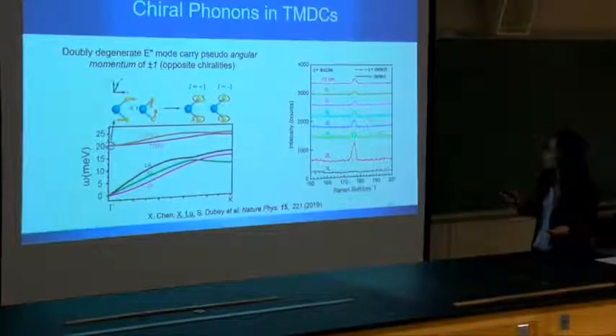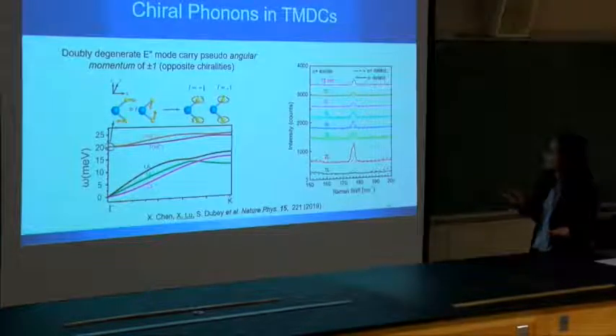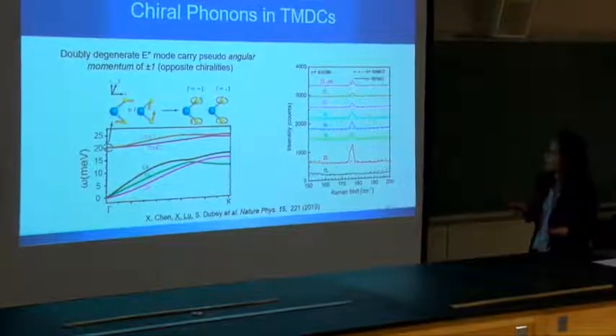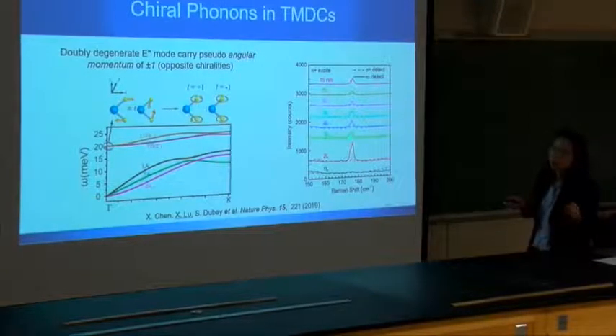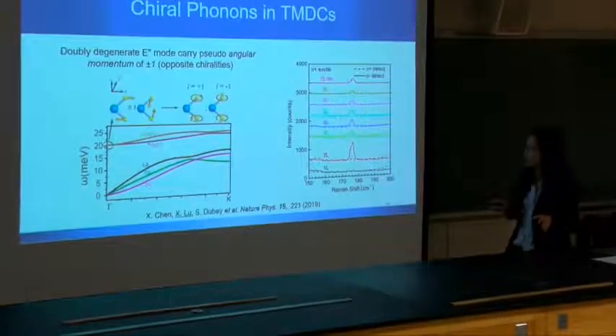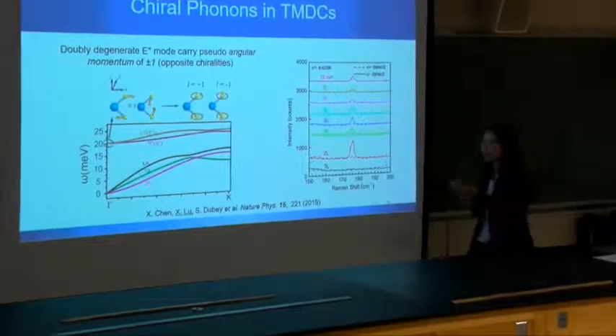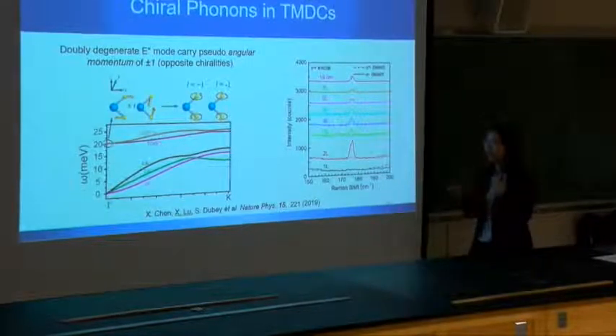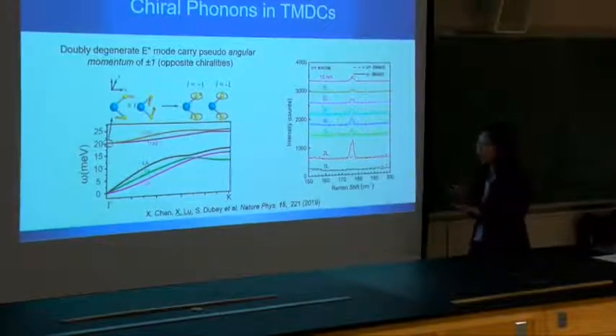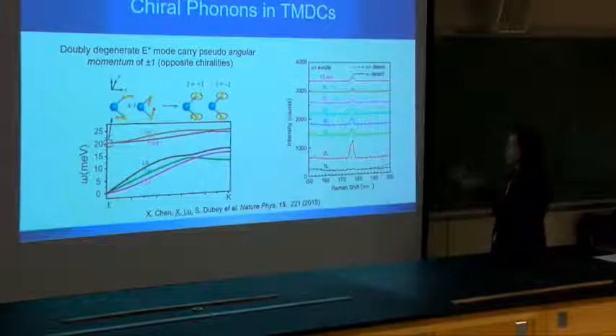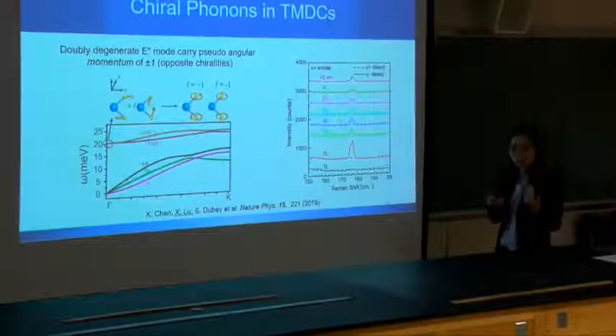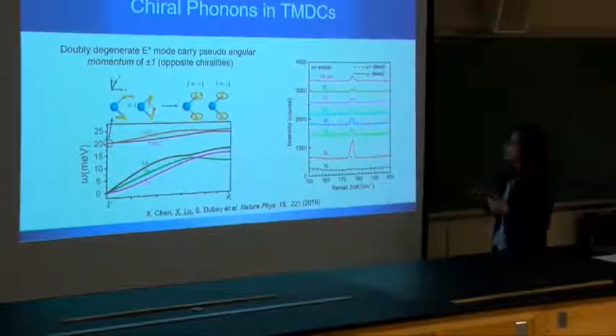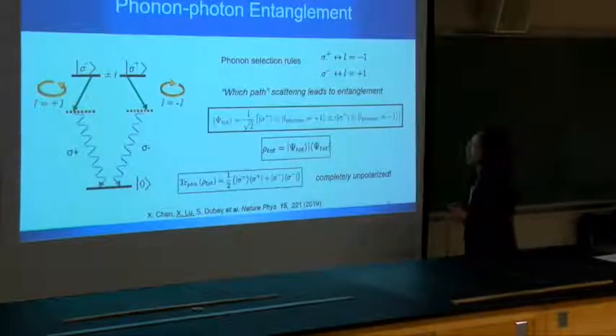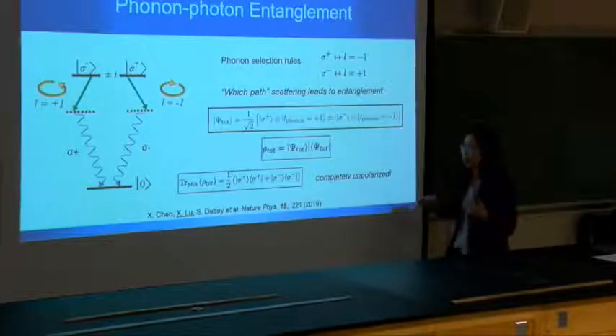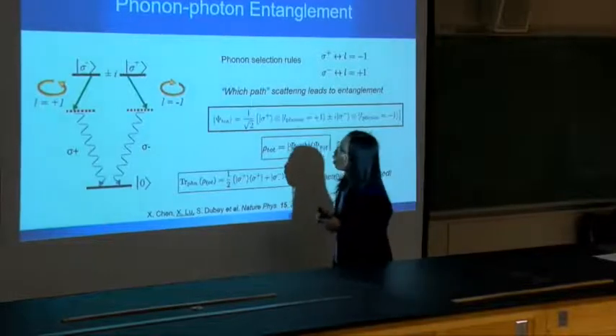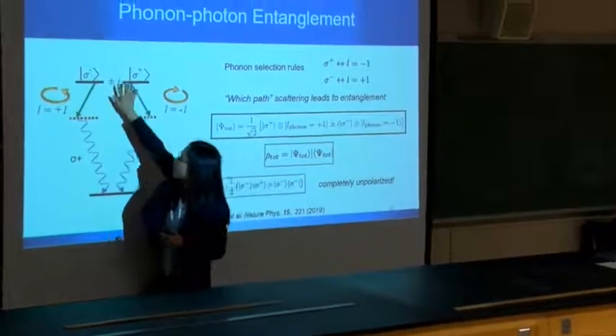But in fact, we see the phonon from the opposite helicity. From the co-polarized, we didn't see it, which means that the phonon scattering carries a chirality, or carries an angular momentum, that makes the scattered light change from sigma plus to sigma minus. So how is this related to the unpolarized emission? So let's start from here.